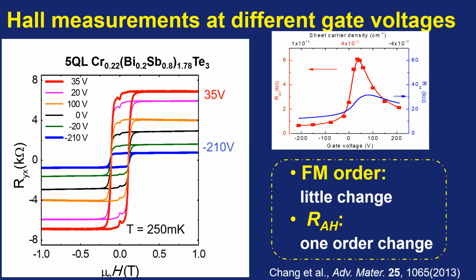In this 5 quintuple layer chromium-doped bismuth antimony telluride, we can see when we tune the gate, the anomalous Hall resistance changes, but the coercive field HC is almost the same. That means the ferromagnetic order has very little change when you tune the carrier density of the sample, but the anomalous Hall resistance has almost one order of magnitude change. In this sample, we can see at 250 millikelvin at 35 volts, the Hall resistance is about 6.5 kilohms. It's almost a quarter of the quantized value. It's still far from the quantized value.